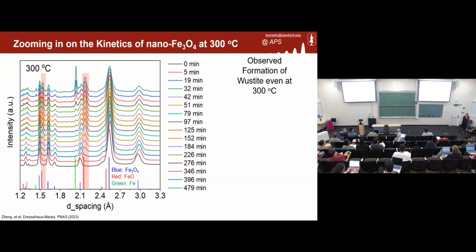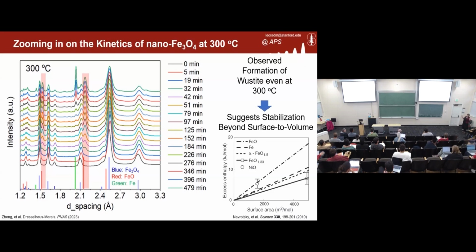Now, I didn't draw too much attention to it before, but actually the wüstite phase is not supposed to form below 590 Celsius. And in fact, you might say, well, nanoparticles, anything goes. Usually the surface to volume effects, i.e. there's way more surface than there is volume in a nanoparticle compared to normal materials. Well, in fact, maybe that should be causing some way of stabilizing that wüstite phase. But in fact, there are these lovely Science papers from the 2010s that demonstrated that it should go in exactly the opposite direction. In fact, it should be destabilized by the surfaces.